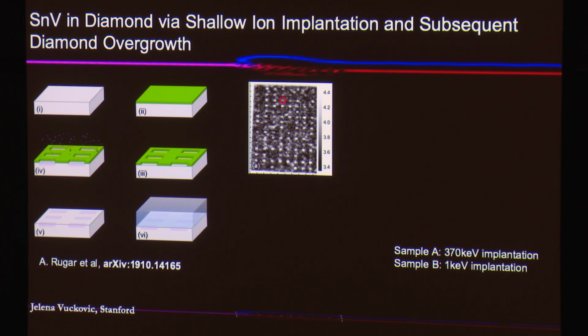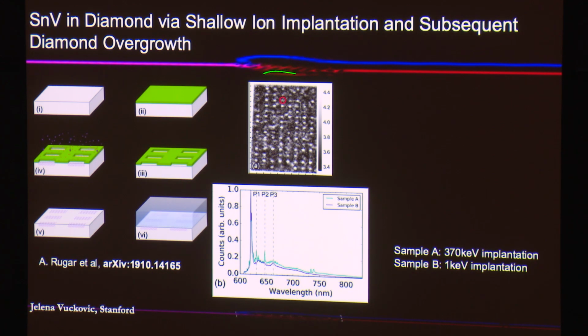And recently, we developed something that we call shallow ion implantation and subsequent growth, where you implant your ions at a very small energy, much smaller than traditional: 1 kiloelectron volt instead of 370 kiloelectron volts. Of course, that leads to shallow implantation, which is not good for your devices, but then you grow a high purity diamond layer by CVD on top. And you can, of course, do mask implantation and introduce them at the desired positions.